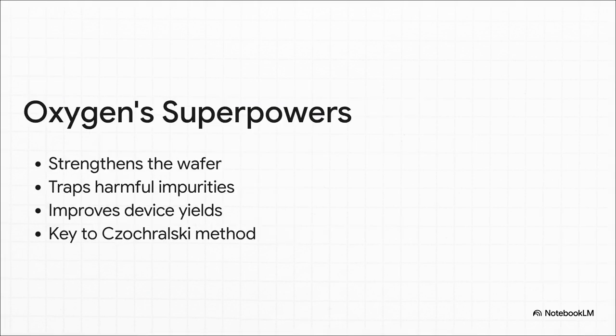What are its superpowers? Well, it makes the silicon wafer physically stronger, which is great, but its main job is this incredible thing called gettering. You can think of it like the oxygen atoms form these microscopic little cages, and these cages are perfectly designed to trap those nasty metallic impurities, pulling them away from the important areas of the chip where the transistors are. This one trick dramatically improves the yield, meaning more working chips per wafer, and it's a huge reason why the modern method of making silicon is so successful.